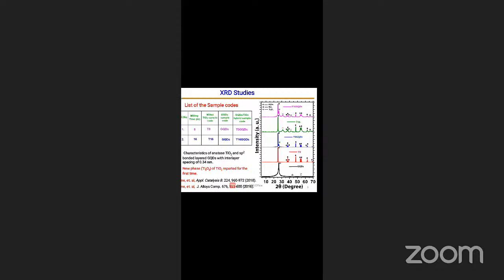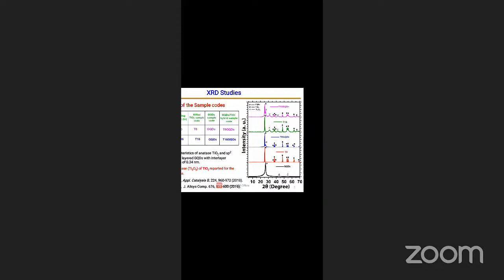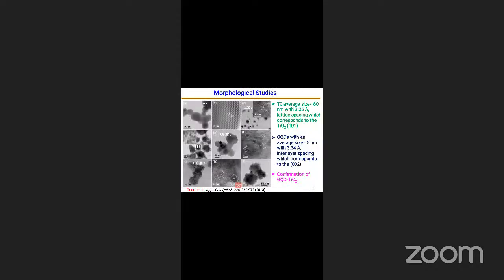So next, this first figure is showing the TiO2 nanoparticle without ball milling. That T0 is showing a particle size of around 80 nanometer. The corresponding IFFT image, that is B, is showing 3.25 angstrom, which is the plane 101. Okay. Next, figure C is showing the graphene quantum dots, with an average size of 5 nanometer, and the layer distance of 3.34 corresponds to the interlayer.